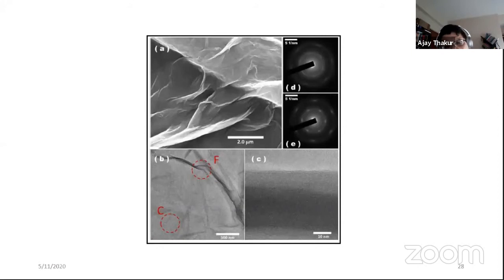So here we see a typical SEM image in panel A for a sheet of graphene oxide deposited onto a substrate. And this is the kind of wrinkles or crumples which I was talking of. In case of graphene which is freestanding or in a solvent, these kind of wrinkles or folds are natural, and a similar kind of behavior is also seen in graphene oxide.